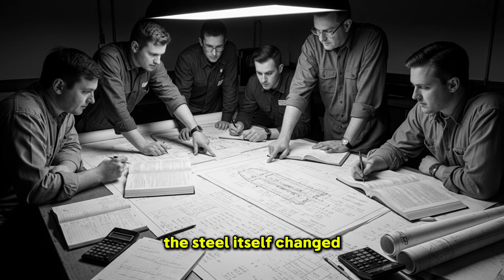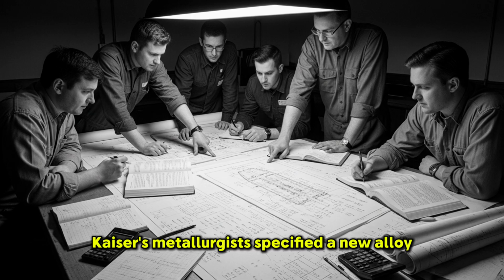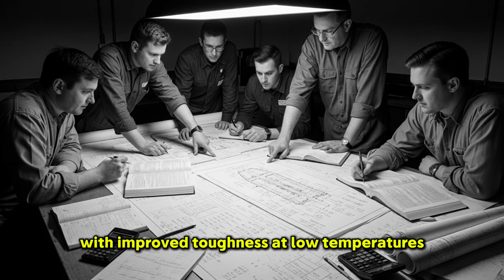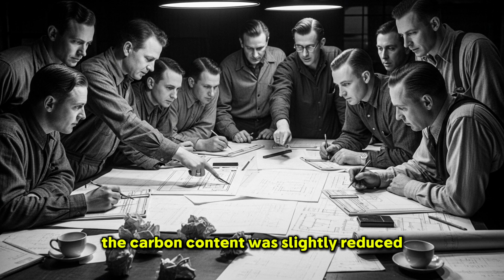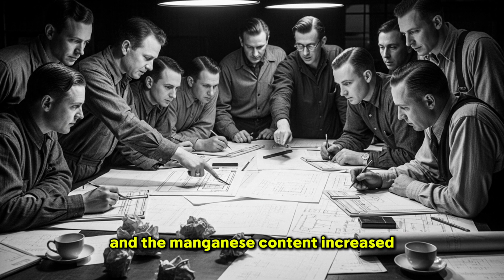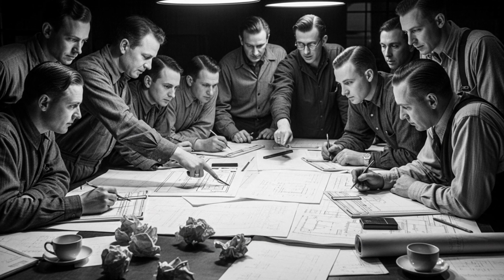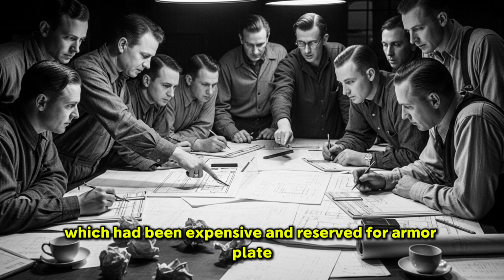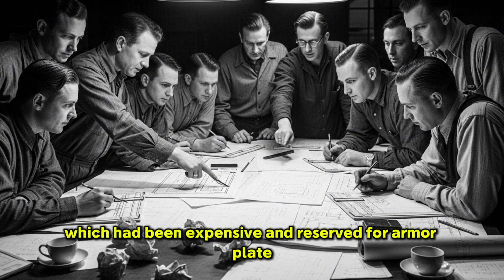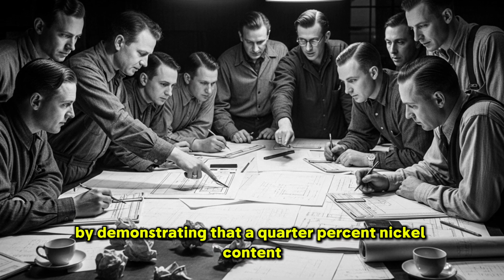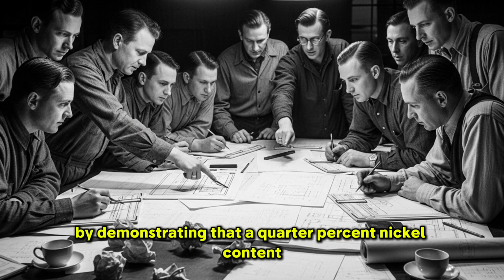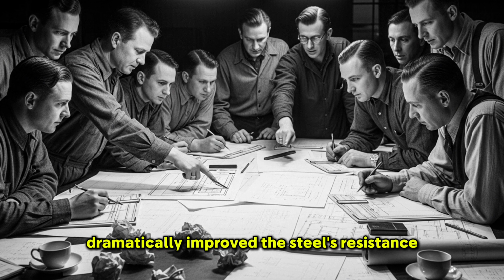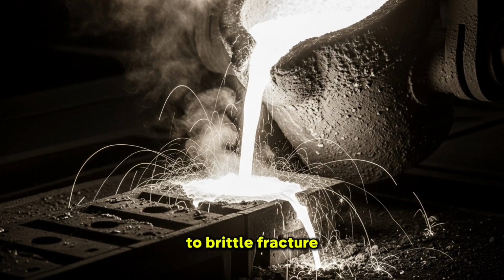The steel itself changed. Kaiser's metallurgists specified a new alloy with improved toughness at low temperatures. The carbon content was slightly reduced and the manganese content increased. Small additions of nickel, which had been expensive and reserved for armor plate, were justified by demonstrating that a 0.25% nickel content dramatically improved the steel's resistance to brittle fracture.